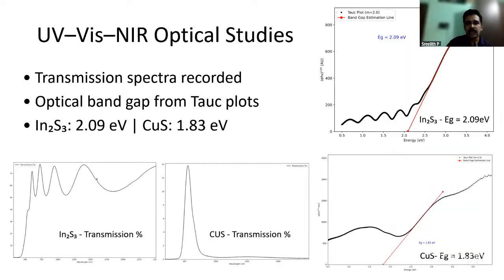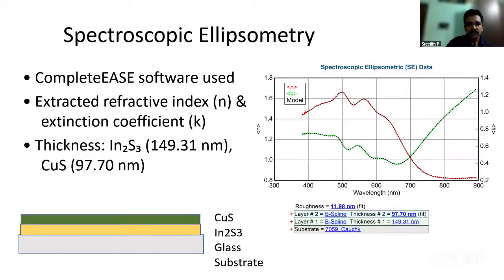UV-visible-NIR transmission spectra were recorded for all thin films. The optical band gaps were determined using Tauc plots. The band gap values were found to be 2.09 electron volt for In2S3 and 1.83 electron volt for CuS. These band gap values indicate that the materials are suitable for optoelectronic applications.